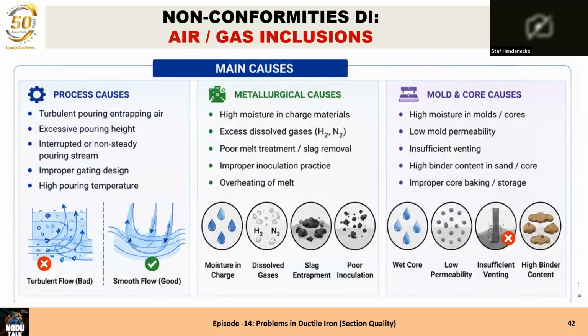So how does it come? It's turbulent pouring of gas. An excessive pouring height can increase the problem. An interrupted or non-steady pouring stream is one of the most frequent reasons for this. An improper gating design, and with the gating design we also mean venting, because by gating we mean the complete system, and the venting is really very important. And a high pouring temperature means that the gas or the air can move all over, and the high pouring temperature can penetrate the coating from a core or the mold, and when it's penetrated and the hot metal comes in contact with the core, you will have gas from the core. So pouring temperature is very important here.